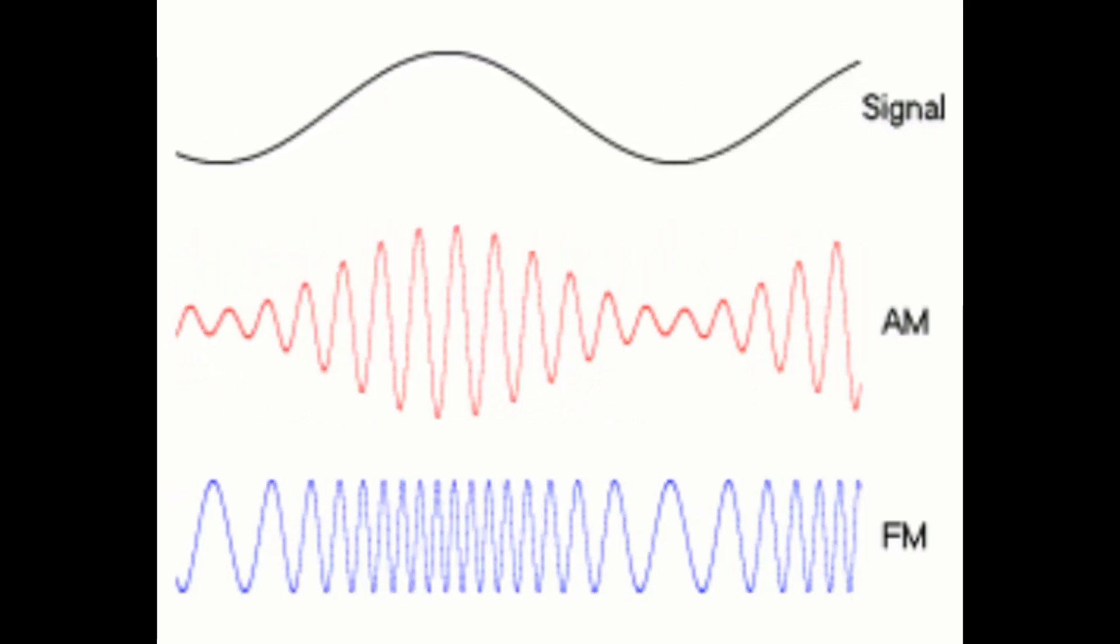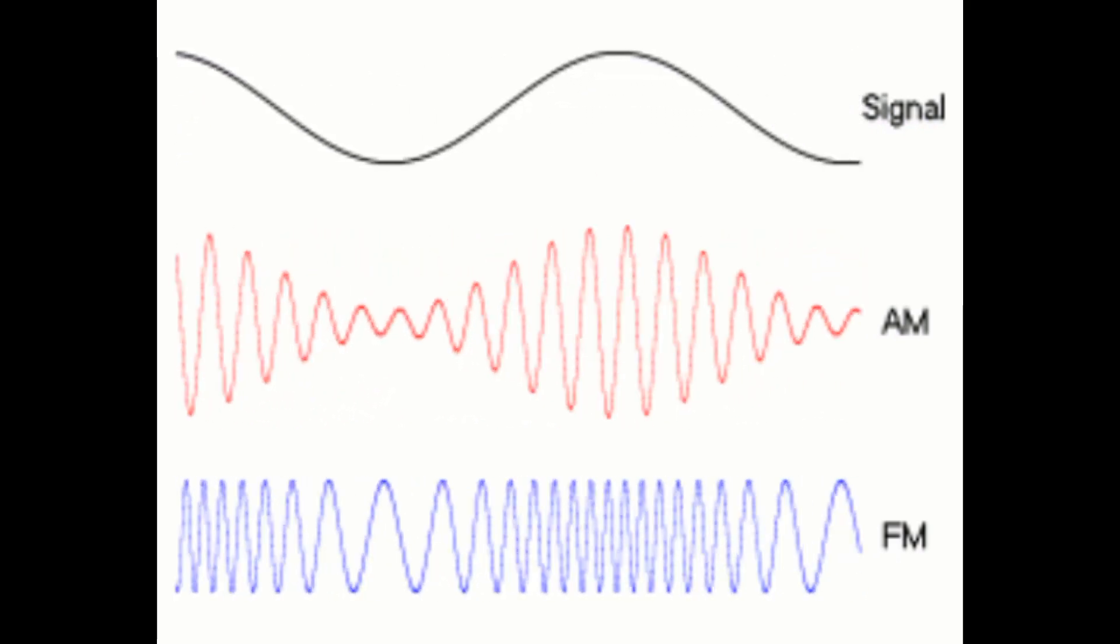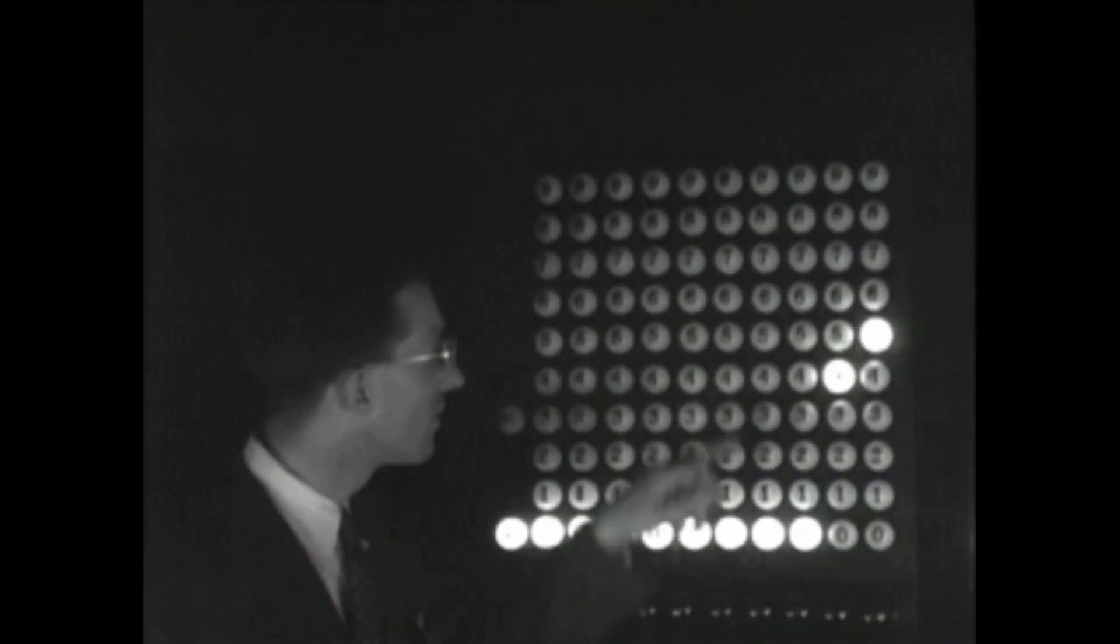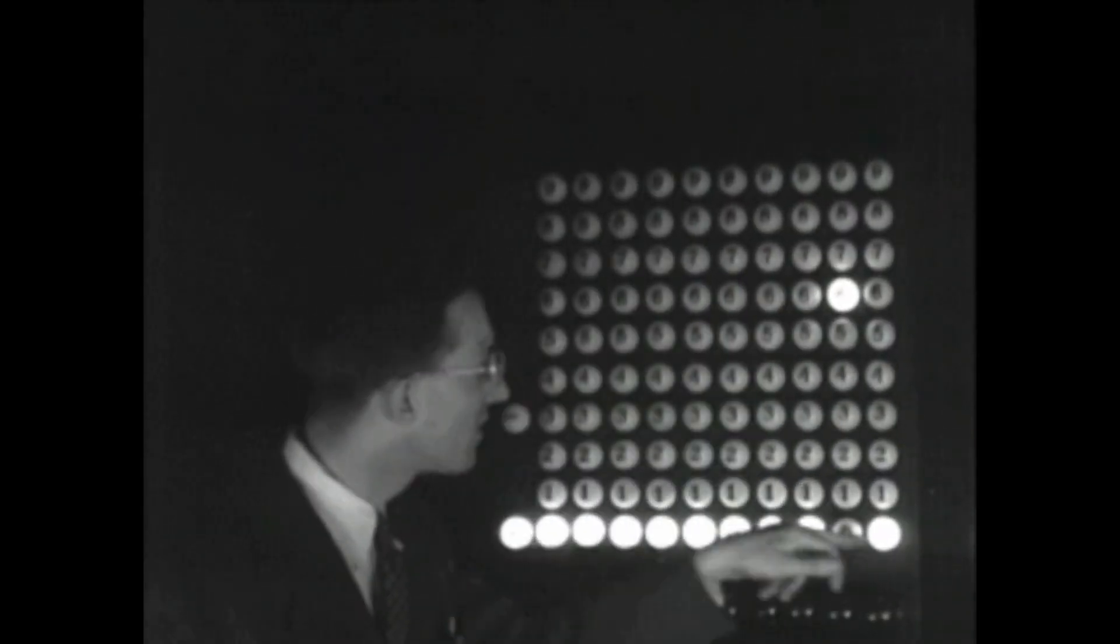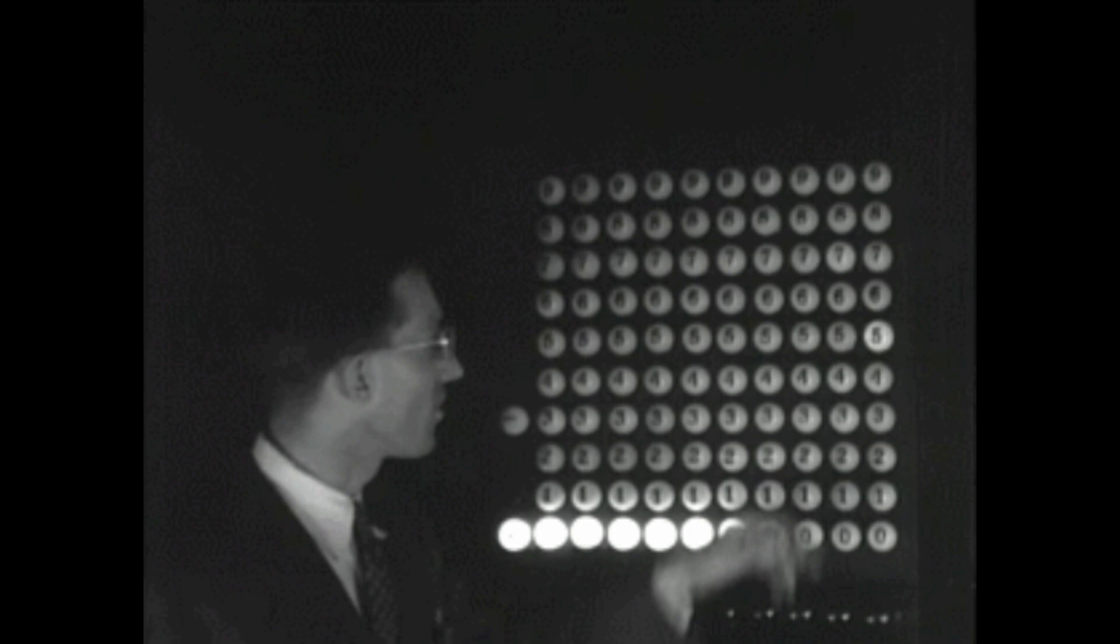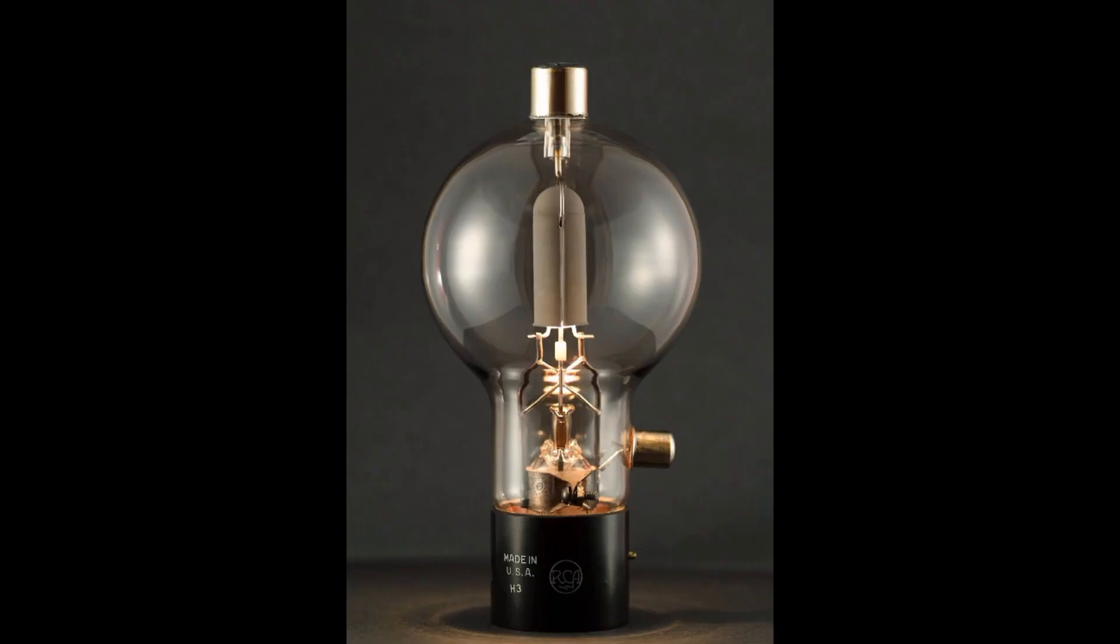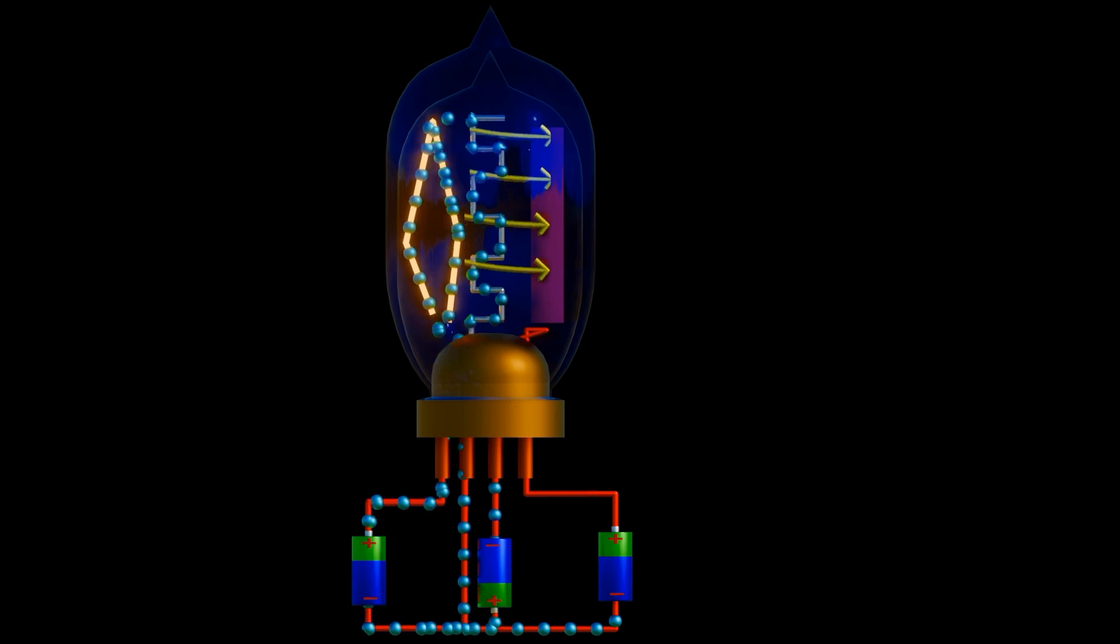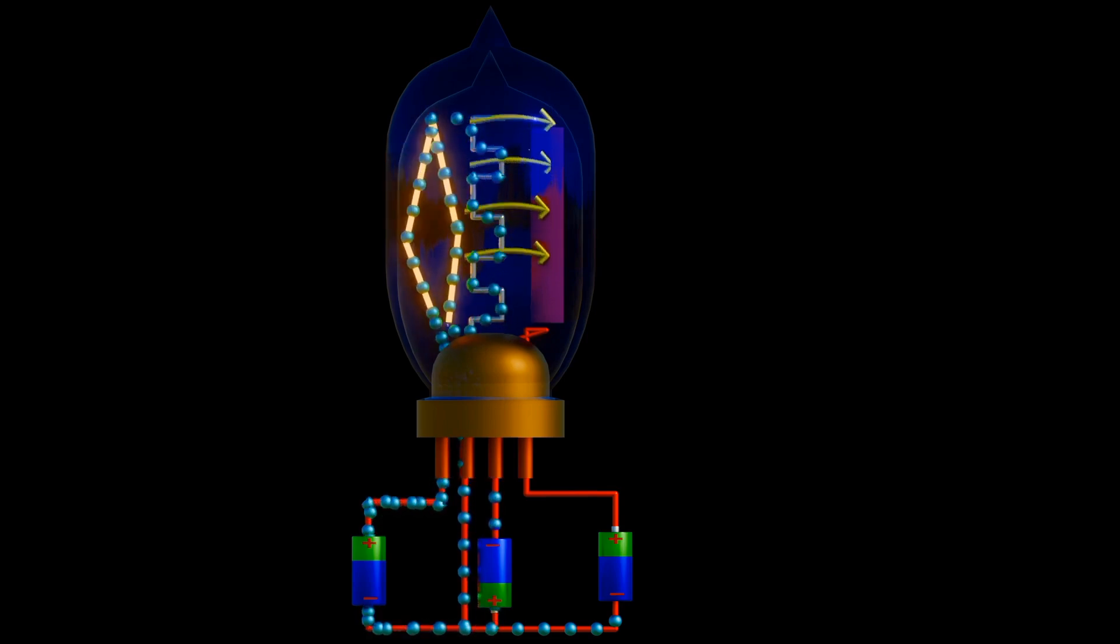Tubes found use in signal applications, which used a relatively lower voltage, and in power applications. Where the voltage were larger, a coating of barium or strontium oxide was used when the anode was operated at less than 400 volts. At higher voltages these emitters were damaged, so tungsten or thoriated tungsten was used. For power applications, these materials could withstand temperatures as high as 2,400 degrees Celsius.